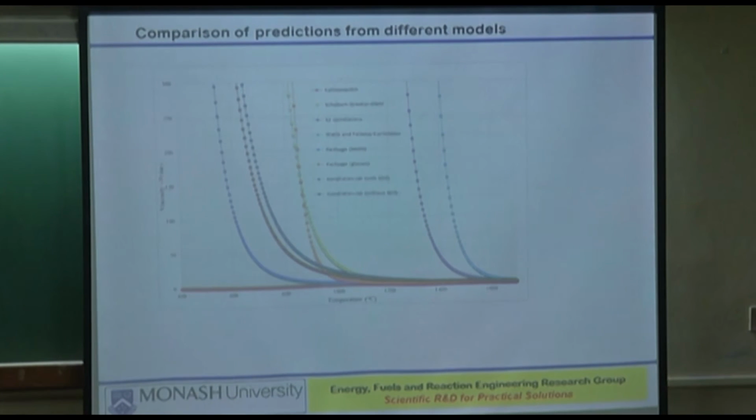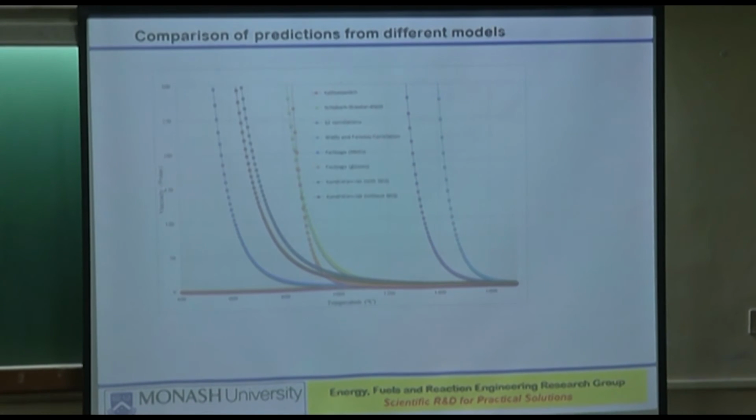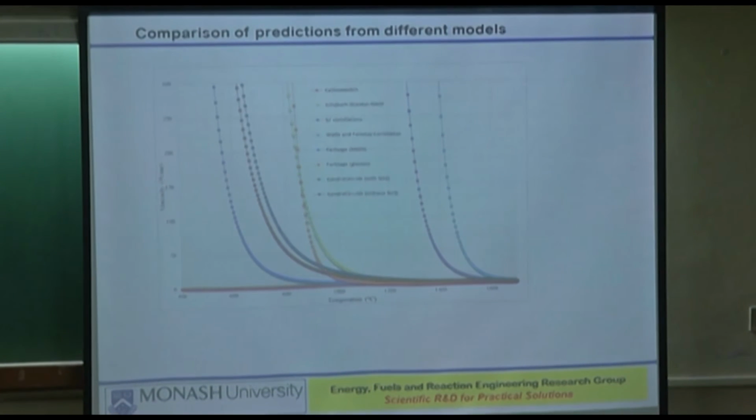Then hydrogen and CO, we decided that because we will have to do the experiments over a very long period of time, each experiment, if it is successful, will take 16–17 hours. We cannot afford to have hydrogen and CO going there for 16 to 17 hours at that temperature.